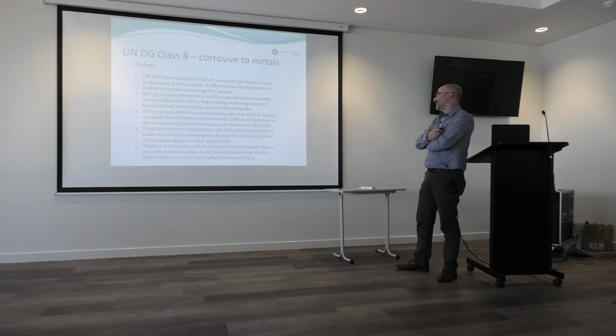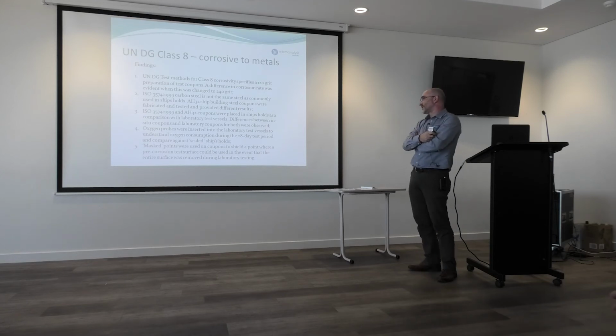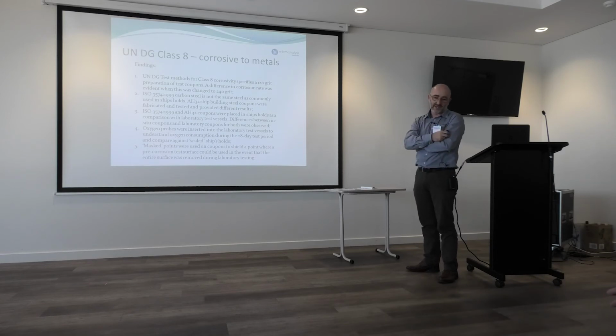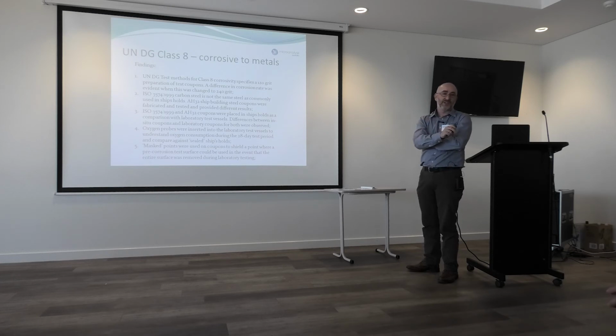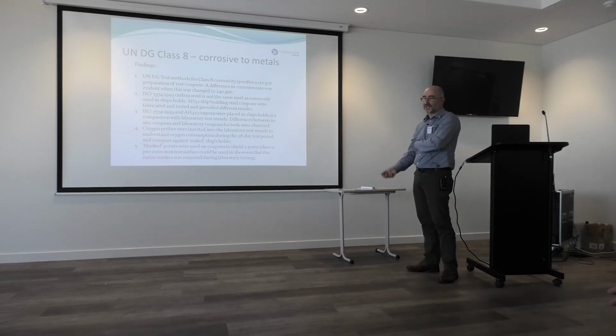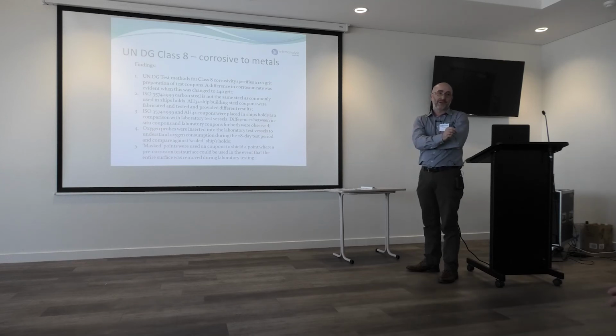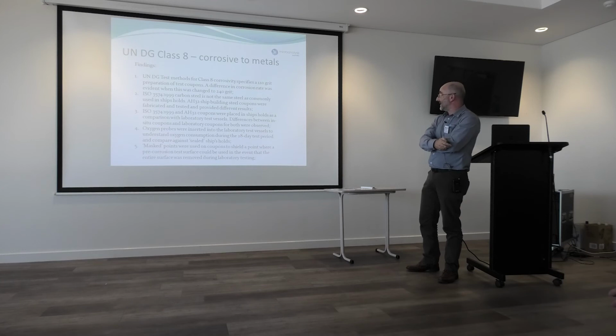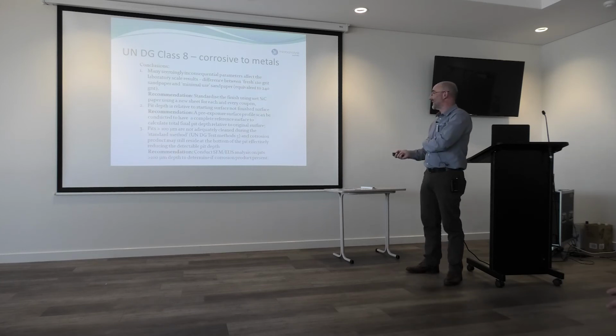The 0.5 there was a bit of a funny one because some of the coupons were corroding so badly that we had no reference surface to work with, so we ended up having to work with some epoxies and other polymer two-pack paints to try to get a shielded reference point so that at the end of the 28-day test we still had some original surface, and what we found worked best was pink nail varnish. And I got a good photo of us all doing our Rocky Horror Picture Show with it, but I wasn't allowed to put it up.